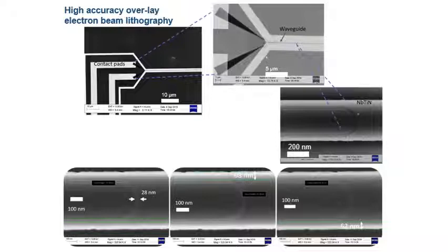And we can see by measurements here that the thickness of these nanowires, we could get them down to 30 nanometer, and the overlay accuracy, if you look at this, is better than 10 nanometer. It was supposed to be right in the middle, but on top we measure around 68 nanometer. On the bottom side we measure 62 nanometer. So the inaccuracy is roughly 3 nanometer in this case.